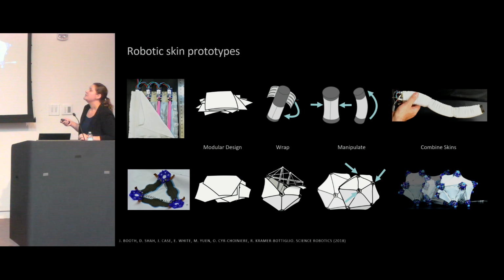So we used an elastomer substrate as our carrier substrate, and then we embed our sensors within the substrate. So you can't quite see them. They're behind these pink McKibben actuators, but you can see the signal conditioning boards sticking out. And those are attached to our sensors. Again, they're transducing capacitance into voltage. And then what you can see more clearly are the McKibben actuators. So these are pneumatic actuators that linearly contract when we inflate them, when we increase pressure.